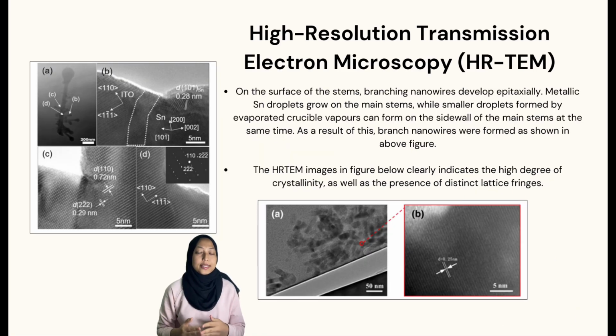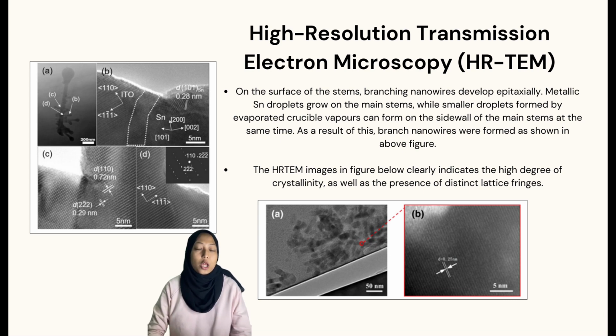The figure represents the HRTEM image on the surface of the stems. Branching nanowires develop epitaxially. Metallic Sn droplets grow on the main stems, while smaller droplets formed by evaporated crucible vapors can form on the side wall of the main stems at the same time. As a result of this, branch nanowires were formed as shown in the above figure.